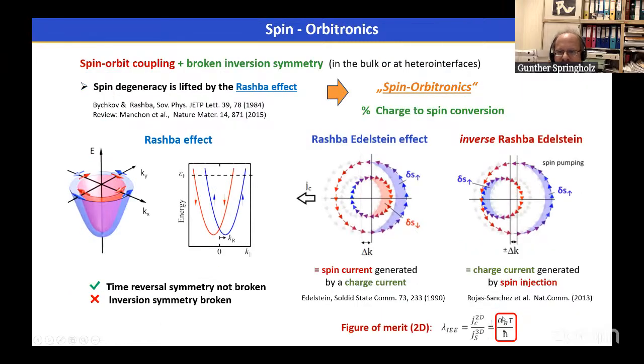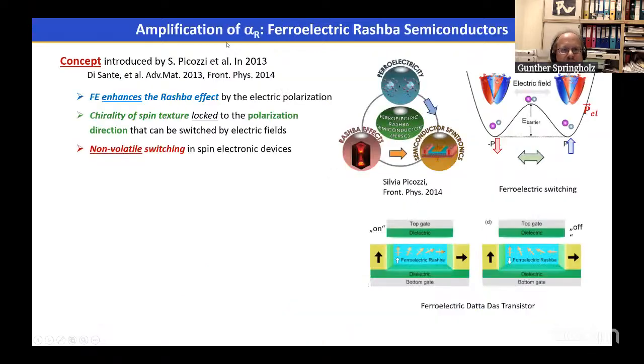Now, as I said, we need a system with a large Rashba constant to have a large Rashba-Edelstein effect. And a way to produce a system with very large Rashba constants is to use ferroelectric materials. This concept was introduced by Silvia Picozzi in 2013. So she showed that in ferroelectrics, this Rashba effect can be very large. And the reason for that is that in a ferroelectric material, we have an electric polarization that breaks inversion symmetry.